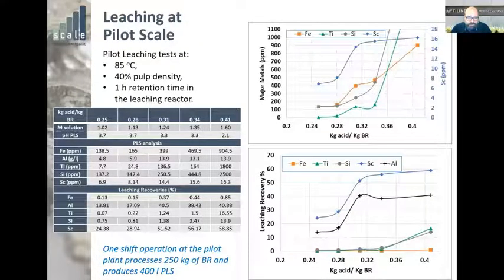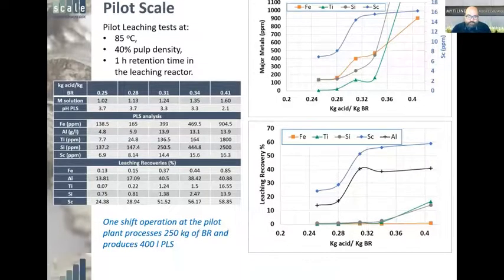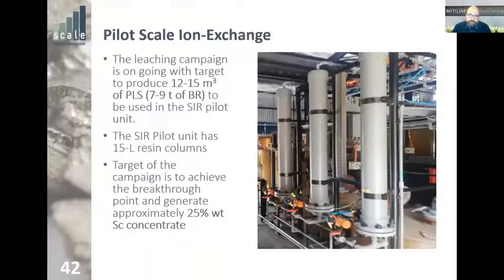In our pilot plant, we are able to process 250 kilograms of bauxite residue in a single shift, producing around 400 liters of pregnant liquid solution. And our target for the leaching was to produce enough pregnant liquid solution to do at least 2 cycles in this ion exchange pilot plant, which is also installed in Greece. So we're housing it for this project.